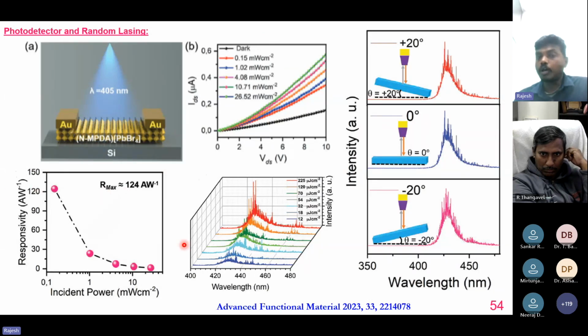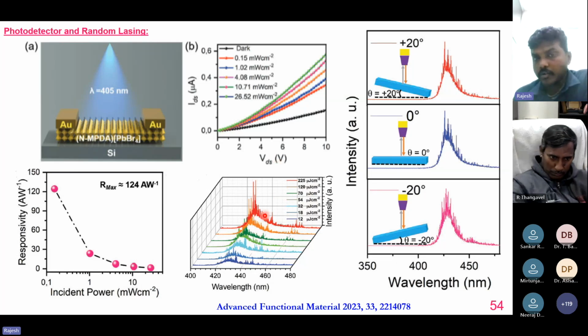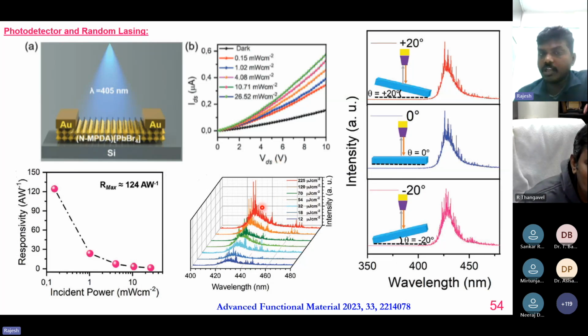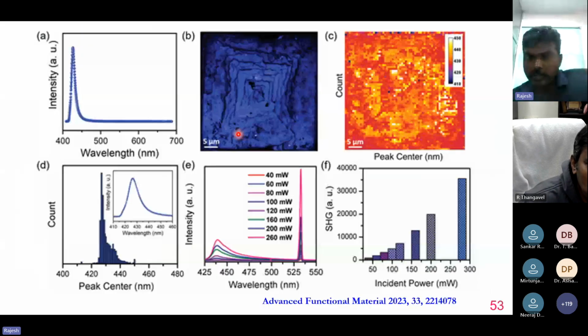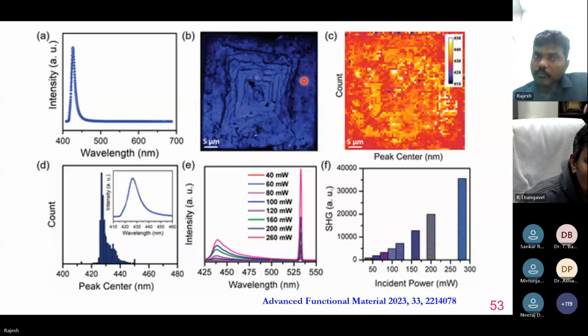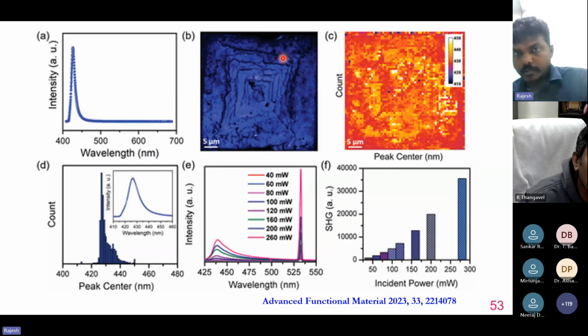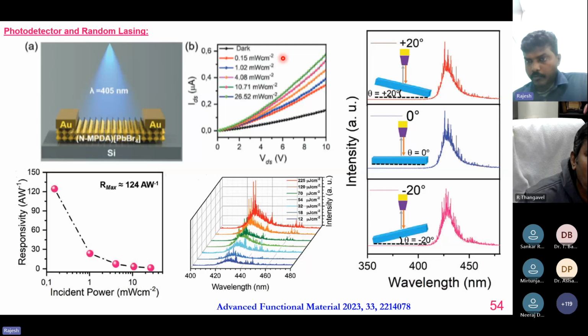And we also showed for the first time that this material can have a random lasing phenomenon. We can clearly observe in the photoluminescence a lot of small spikes which indicate lasing is happening in our material. This is because our material has a pyramid kind of structure. The irregularity of the steps helps the random lasing phenomenon to occur.